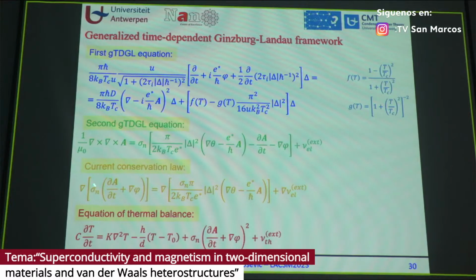So when we apply current to the system, which is what we want to do with superconductor electronics, we have to solve for the electrostatic potential. So this electrostatic potential, the temperature is here in the first Ginzburg-Landau equation. This is also where normal state conductivity enters, which is a parameter from the experiment. And finally, the equation of thermal balance, where we have the time-dependent evolution of temperature, how fast temperature is changing, how far the temperature change is reaching related to conductivity. And these four equations have to be coupled self-consistently. And this is where we enter the external, for example, gating enters here, or thermal excitation in the case of single photon detectors or laser excited superconductivity and so on.